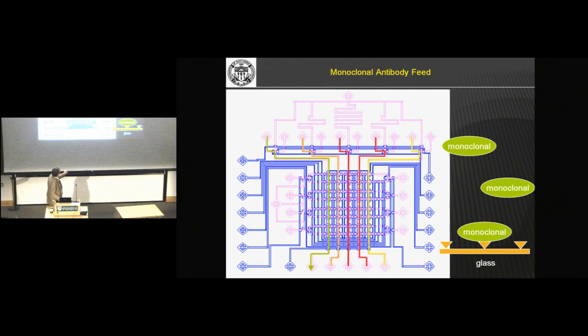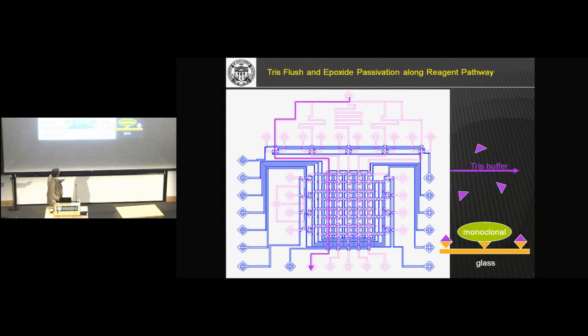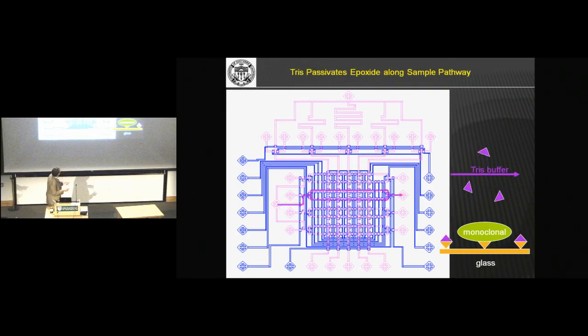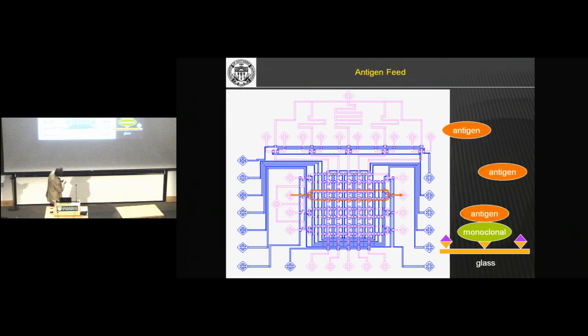We load this up with different antibodies in different channels, and then we put our sample in the perpendicular channel. So basically, by opening and closing these valves, we can either have channels that conduct through like this. That's how we load the antibodies. Then we put our sample in. It goes in the perpendicular direction. And we can pump the sample around. So I now know the volume of my sample. The volume is about 0.5 nanoliters. And I can move that 0.5 nanoliters over my surface functionalized surfaces many, many times and collect all of my proteins on them.